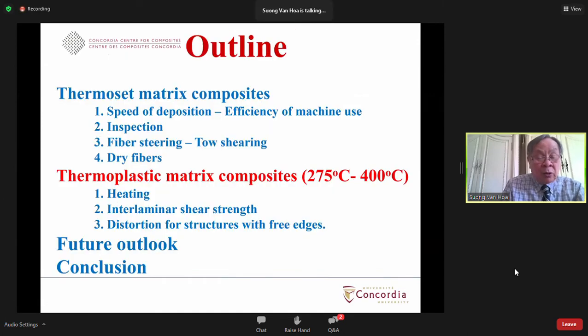So next here, I talked about the use of AFP to make thermoplastic composite. So thermoplastic composite depends on the kind of resin because of the fact that you have high viscosity. And so that means you need to really heat it up to high temperature in order to reduce viscosity. And so depending on the kind of matrix that you have, whether you have the PEI, PPS, or you have PEEK, then the process temperature can vary between 275 to 400 degrees centigrade. So thermoplastic composite certainly has more issues than the case of thermoset.